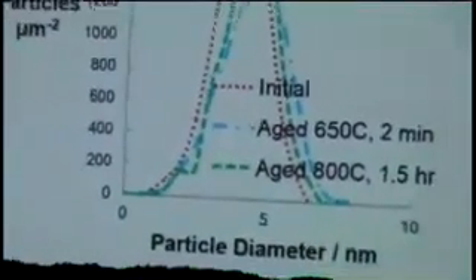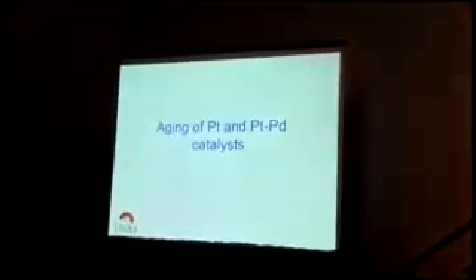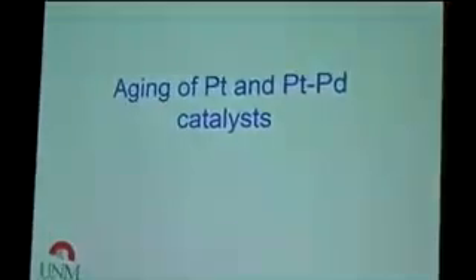You heat palladium, and very quickly it forms an oxide. The nice spherical particles become irregular in shape, and after that we can see very little change in particle size distribution. Whatever change happens in the first 2 minutes, that's when you see a big change in the number of particles dropping. After that, it's pretty stable. Okay, palladium oxide is very stable at 800 degrees.